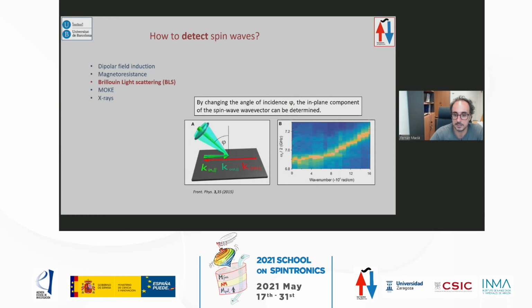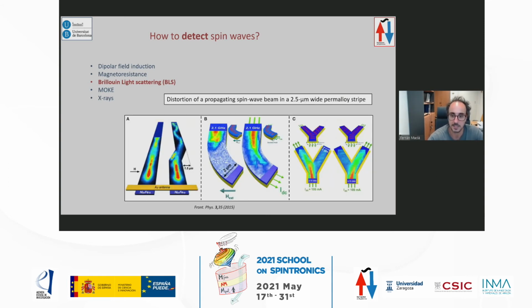By doing this, you can directly map a system and make this nice graph that you can see here, which is frequency versus wave number. And you don't have to excite anything. You just shine light, you change the incident angle, and the incident angle sets the spin wave vector that you can be sensitive to. What you are detecting are just thermal spin waves. So this is just a way to characterize any thin film or any magnonic device.